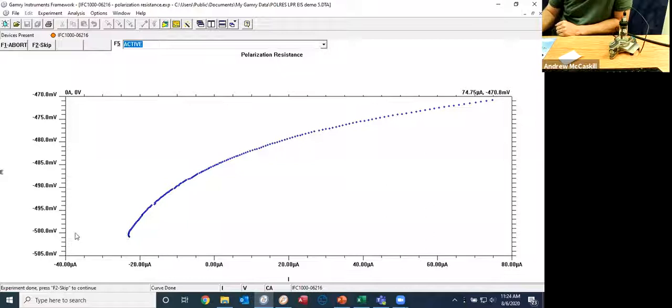So here we are, just above minus 500 millivolts. So here would be 486, and as we come around here, look, at 486, we're very close to zero current. So all of these are just good indicators to take mind of, and then from 486 we'd go down to about 470. So we're definitely scanning over the window that we defined, and at 486, our open circuit, we're very close to 0 amps. So that's just a good indicator that we probably collected some pretty good data.